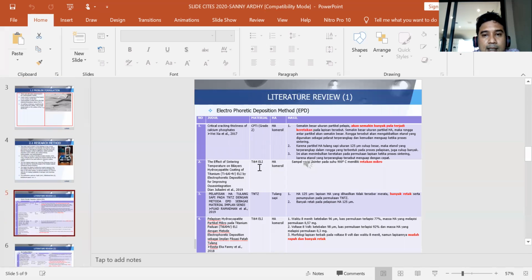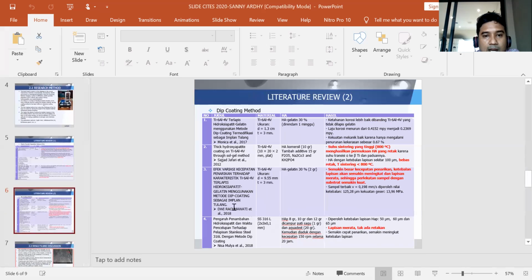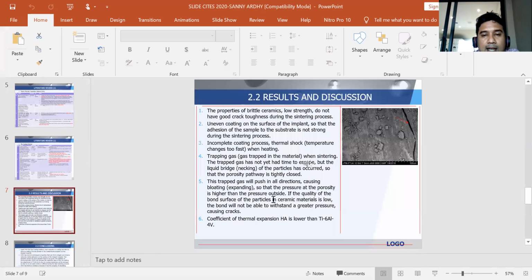This is a literature review on my research with the electrophoretic deposition method and dip coating method. Results of my research are the properties of brittle ceramics, low strength, not having good crack toughness during the sintering process, and uneven coating on the surface of the implant, so that the adhesion of the sample to the substrate is not strong during the sintering process.